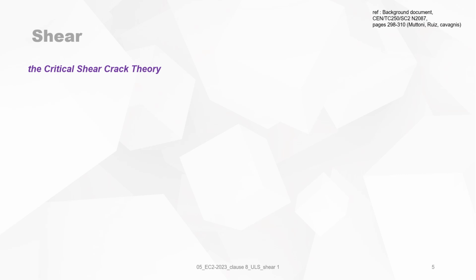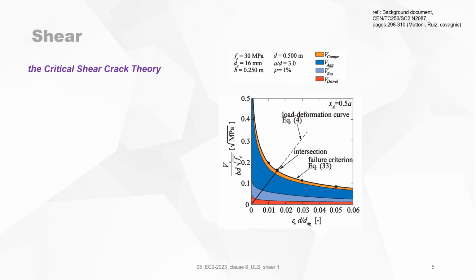The critical shear crack theory is based on a shear crack criterion. And this criterion is derived as follows. On the x-axis, you have the strain of the reinforcement multiplied by d over dg. And on the y-axis, you have Vc divided by bd, which is the shear stress, divided by the square root of the compressive strength of the concrete. So the unit is square root megapascal. When you investigate a shear crack and you apply a load deformation curve, then for different load cases and deformation curves, you will end up, for instance, this is the load deformation path, and you will end up here with a failure of the structure.